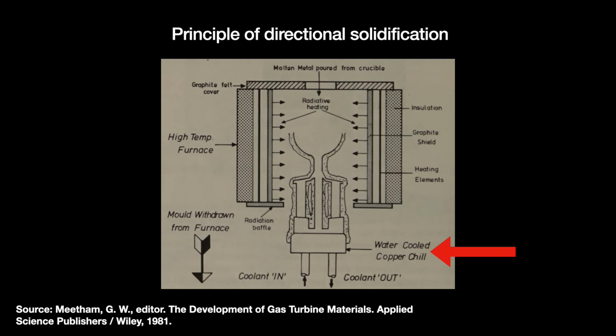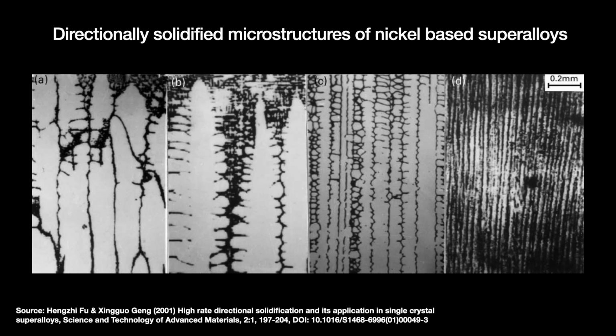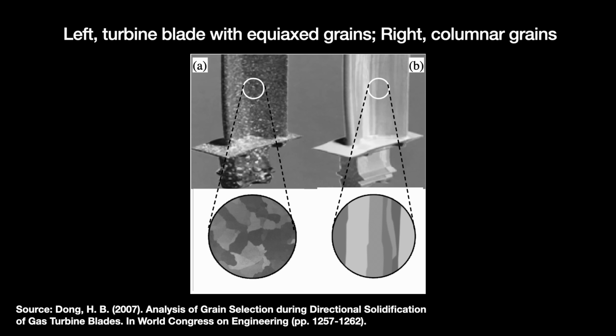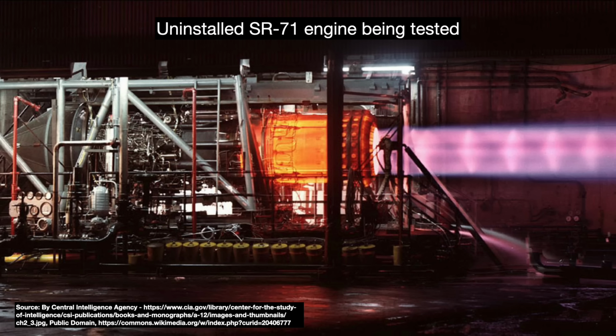The melt pouring in at the bottom touches the chill plate and crystallizes. Then slowly and deliberately, we move the cast and the melt inside of it downwards out of the furnace. If done right, then the melt crystallizes from the bottom to the top, growing these tall, straight vertical crystal columns. The grain boundaries going left to right are largely removed, leaving only those parallel to the blade's length, running along the turbine blade's major stress axis. Pratt & Whitney first used directionally solidified superalloys to produce the turbine fan blades for the J-58 engine in the Lockheed SR-71 Blackbird plane. I am told that this airplane is mildly famous.